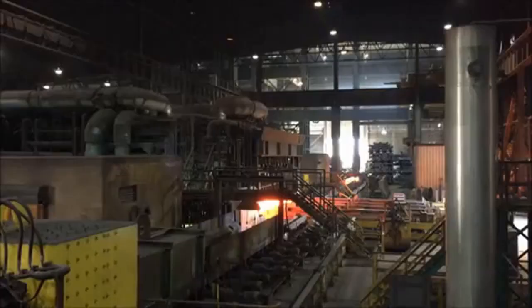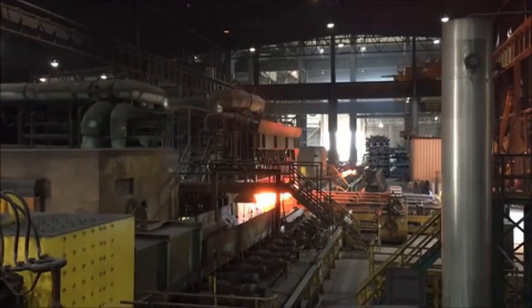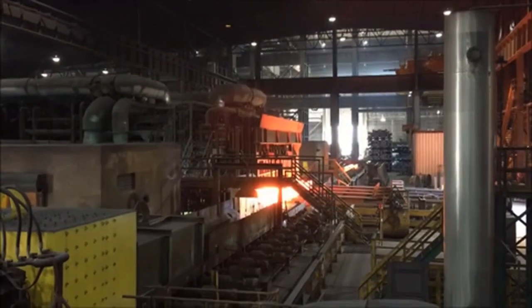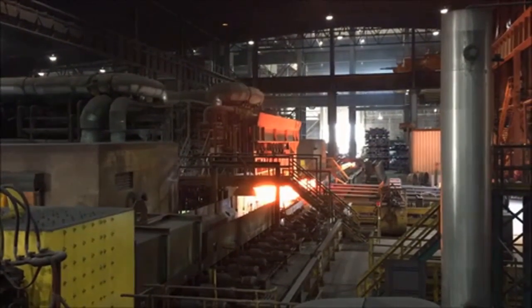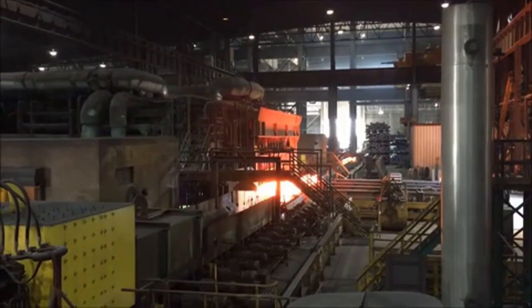And I have a picture here of a beam blank coming out of the reheat furnace, out of the discharge side of the reheat furnace. You're going to see it lifted out in this yellow box that's on the left lower corner. That's called a descaler, and that blows off the oxides that formed at the high temperature, basically iron oxides that form.